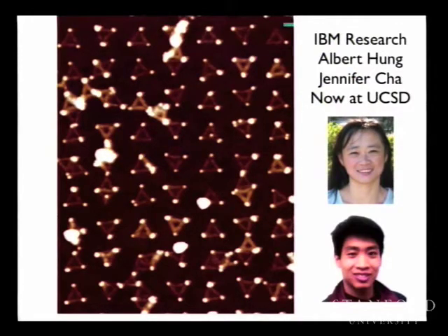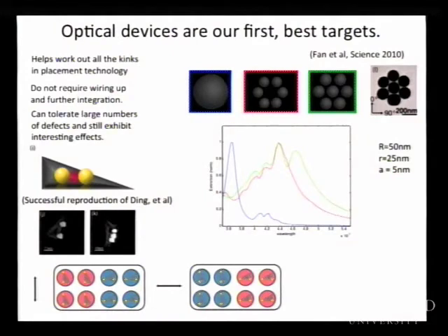So this goes in the direction of placing different materials where you want. And the kind of thing you want to do there is make optical devices, right? I think one of the places that will prove this kind of technology first is in making optical nanostructures. That's because, unlike for carbon nanotubes or nanorods, we don't have to solve translational symmetry problems. We don't have to get them to line up in translation on our structures where we want. We can rely on metal nanoparticles going down at individual points, right?